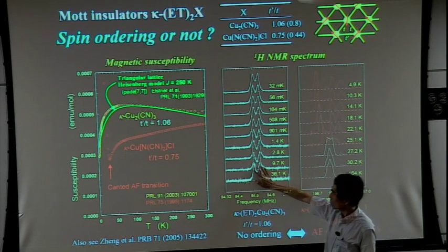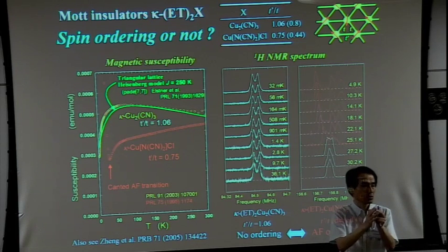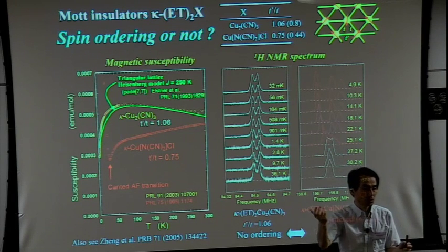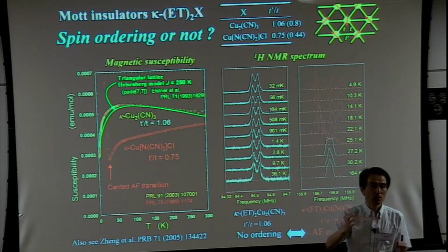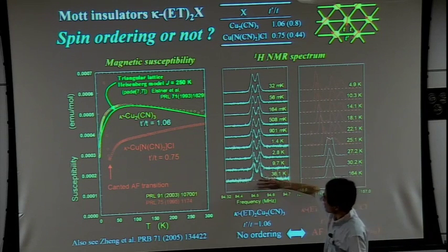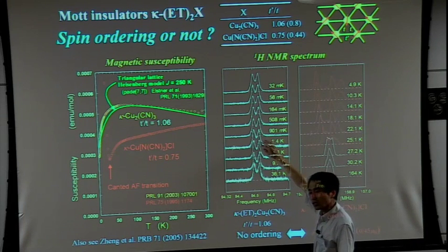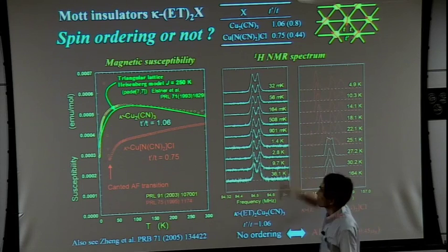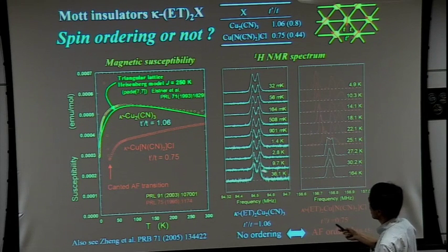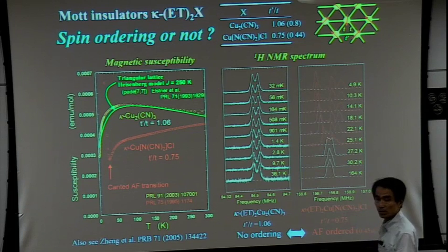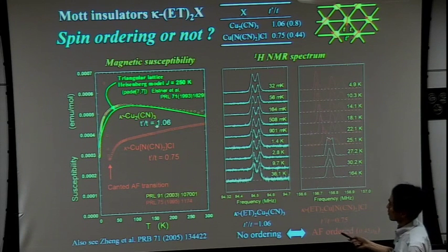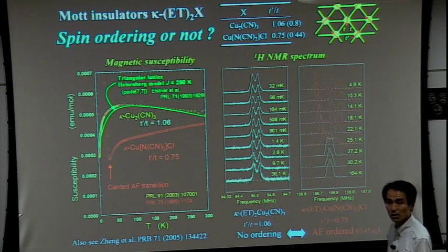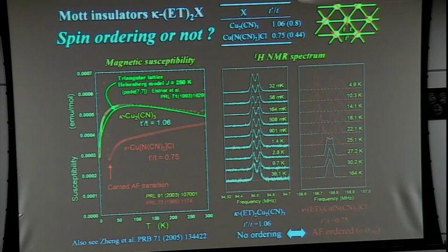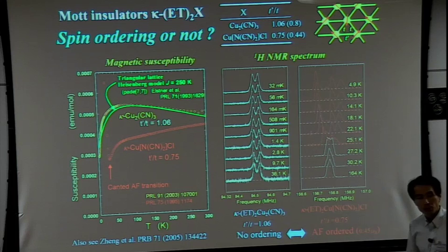But this splitting is due to nuclear dipole interaction, not related to the electronic state. So the important point is whether this spectral shape changes or not when temperature is decreased. You see the spectral profile does not change down to 32 millikelvin, which is 4 orders of magnitude lower than the exchange interactions. So from these experiments, we concluded that a quantum spin liquid is realized in these materials.